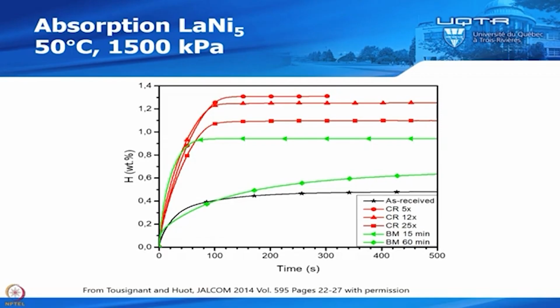And this is what you see on the second absorption. Okay, so on the second absorption, you see that all of them are absorbing at the same rate. So the difficulty is the first hydrogenation. Then you have a difference of kinetic between all of them. But after the first hydrogenation, and this is a common example for many metal hydride, after the activation, then the kinetic is the same. The only thing that is different is the capacity.